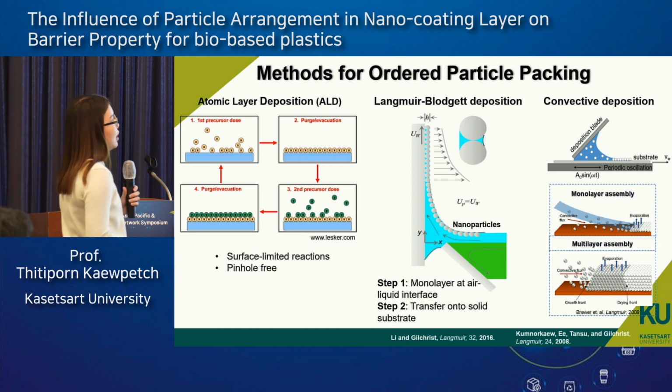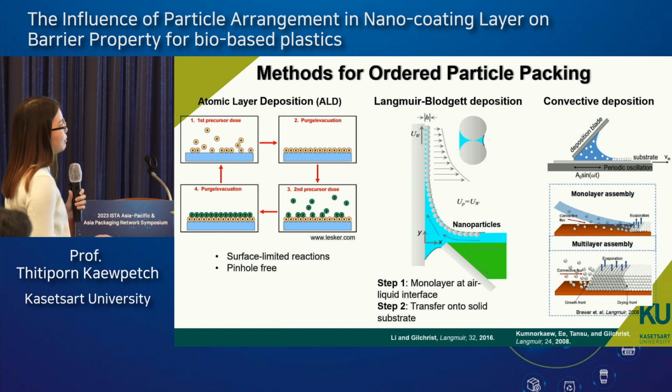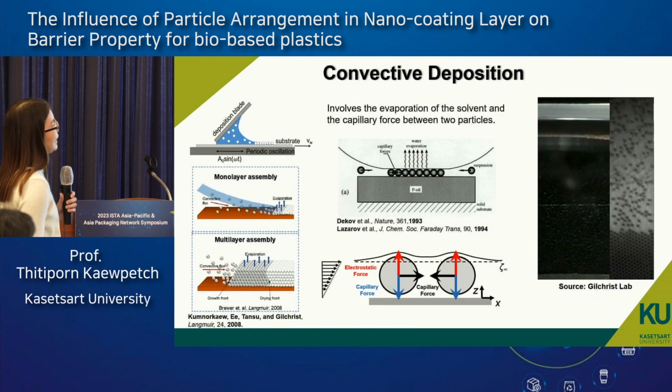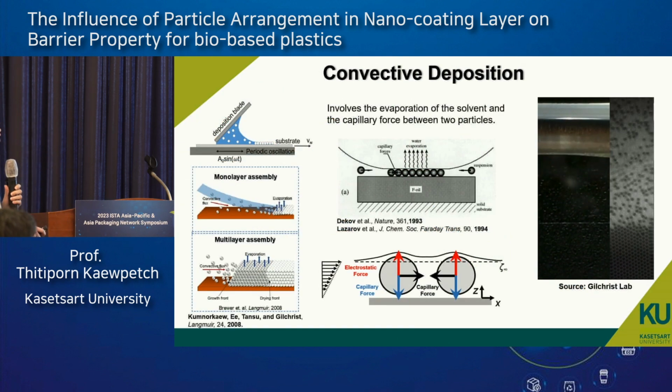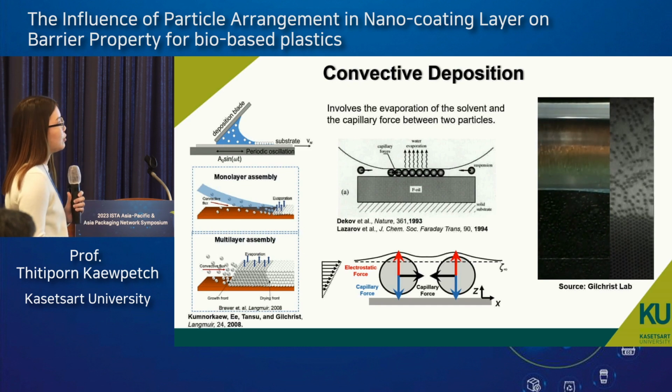Okay, but if you want to make a multilayer structure with this technique, you have to do multiple things. But if you want a monolayer or multilayer, you can use convective deposition. Basically, this technique involves the evaporation of solvent and the capillary force between two particles.